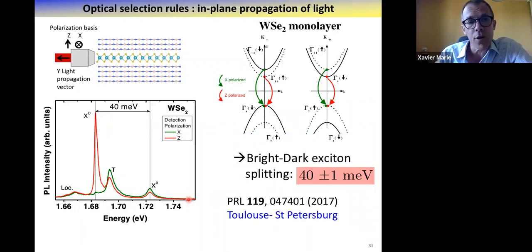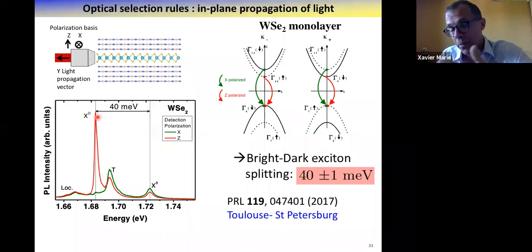And if you measure in green the X polarized, you measure the neutral exciton in the photoluminescence spectra, the trion, but almost nothing else. But now if you measure the Z polarized component, you see that a new line clearly appears at low energy, very clear, and this corresponds to this dark exciton. So the dark exciton is not so dark, it is allowed for Z polarized light, due to the spin mixing with higher energy bands, which I will not detail. So from this, you can identify where your spin forbidden dark neutral exciton is, and you get the splitting between the bright and the dark.